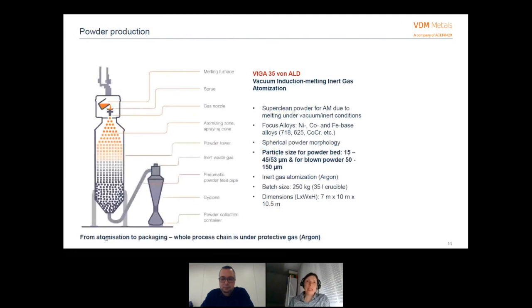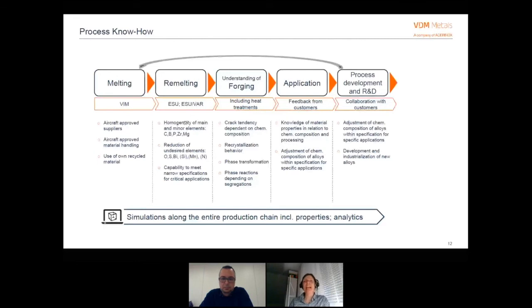How it's usually made is in a melting furnace. You melt your material in vacuum induction melting. You start to cast the material, and with a gas nozzle with argon, usually it's argon, you have the powder go down, and when it comes to the end of the facility, it is melted or solidified, and you can see the powder here. So I go through this point. It would be in the PDF after, sorry for timing, so that is what we discuss. You should understand the whole production chain, because one chemical composition could work for one application but not for another, and that is the point to think about.